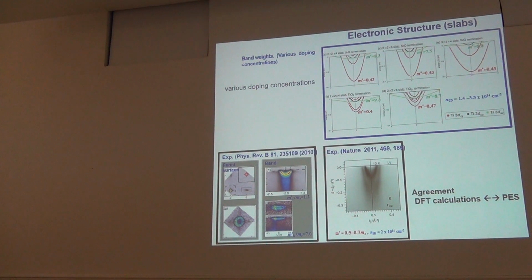And there has been a lot of work done now also for the heterostructures to see the role of the oxygen vacancies. Now people grow, for instance, these heterostructures with what they say oxygen pressure to reduce the number of oxygen vacancies. However, it's very inherent, Paul can say more on that, the oxygen vacancies play an important role in oxides. And here they are, in fact, the key player in order to get this two-dimensional gas of electrons conducting.